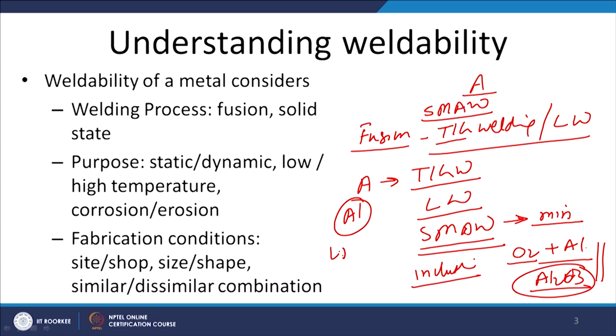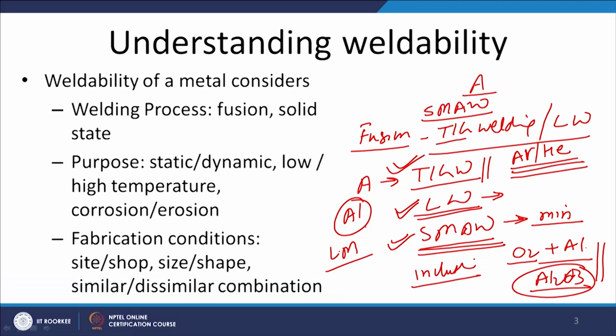So, despite having the low melting point, the high affinity of aluminum with oxygen during welding by the SMAW process will be leading to limited weldability. On the other hand, if the same aluminum alloy is welded by gas tungsten arc welding using a shielding gas like say argon or helium, it will offer excellent weldability because the formation of Al2O3 is avoided by the effective protection from the argon and the helium as a shielding gas. On the other hand, if argon and helium as shielding gases are used during the laser welding of the same aluminum alloy, it will offer the best weldability. But if we consider the cost aspect, then probably laser welding will be costlier as compared to TIG welding, and the cheapest one will be the SMAW. But since the SMAW is not able to develop the weld joint, GTAW can develop the weld joint at a lower cost.